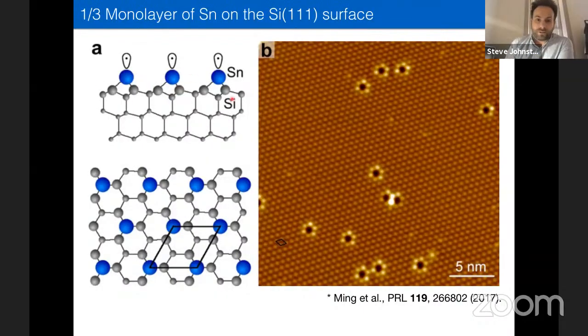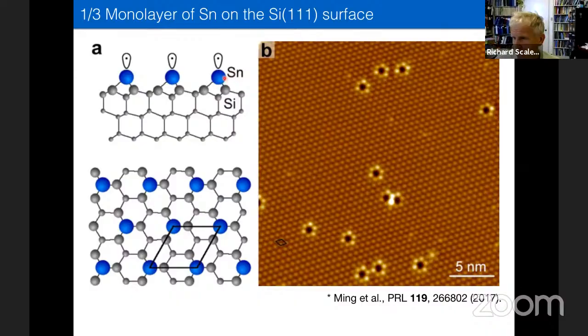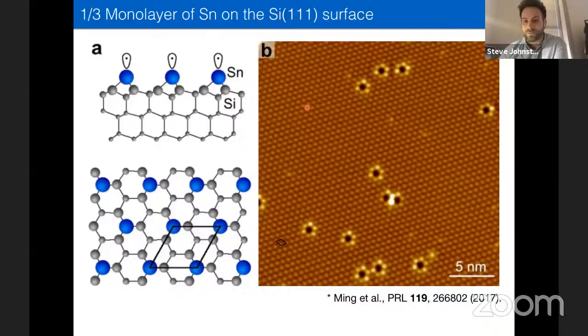So in the parent system, these can be grown in these really nice surfaces covering very large areas. So this is a topographic map of the undoped system grown. You can see it's a really nice triangular lattice. These black dots correspond to tin vacancies, but they're very pristine samples, and they have this really nice sort of flat surface. There's not really much evidence for rippling. This is different from lead atoms on the same surface. The lead atoms on the same surface actually undergo a series of interesting charge ordering and CDW type transitions, which is another interesting subject, but I'm not going to talk about it today.